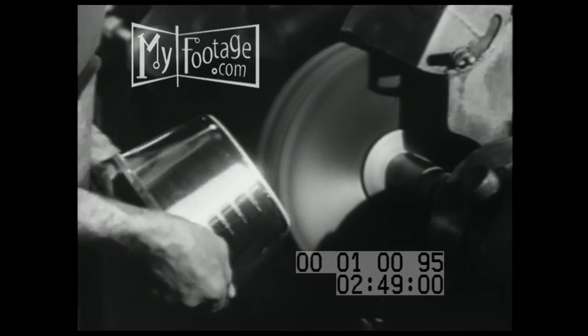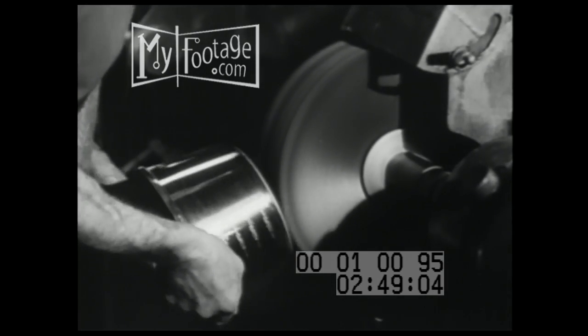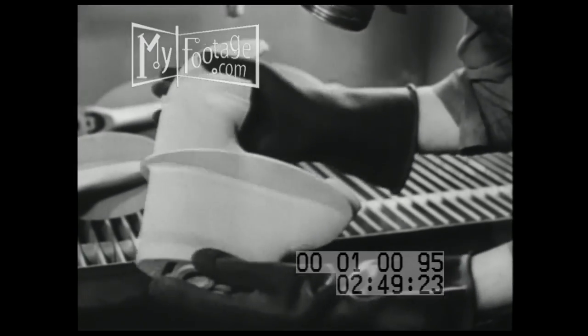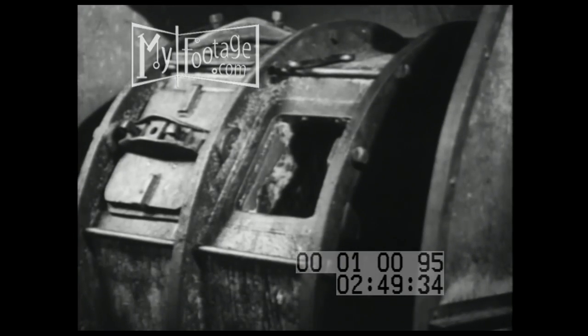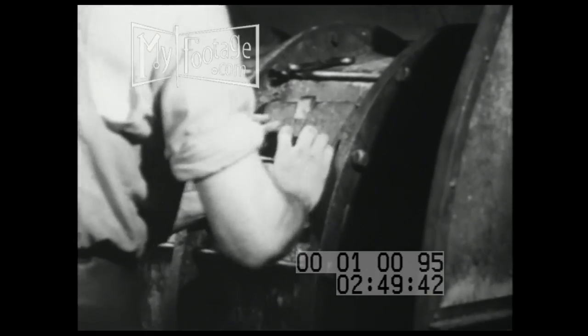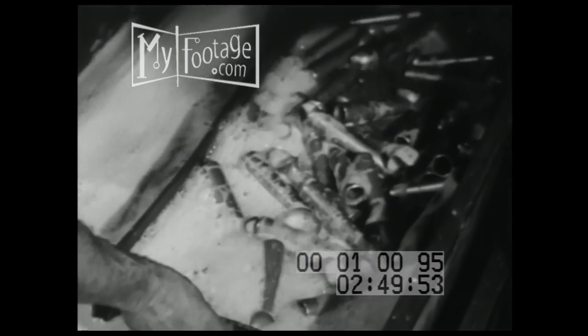A wire brush provides the familiar scratch brush finish with its various effects. The texture of the surface depends on the fineness and stiffness of the wire in the brush. Sandblasting is a fast and inexpensive method of giving castings a clean, uniform surface; variations in the kind and coarseness of abrasive give finishes with variety in texture and shade. The tumbling barrel is a practical method of removing burrs and other roughness from small parts — hard steel shot with a little soap and water tumbled in the barrel results in a smooth and burnished surface, with hundreds of parts finished in the same economical operation.